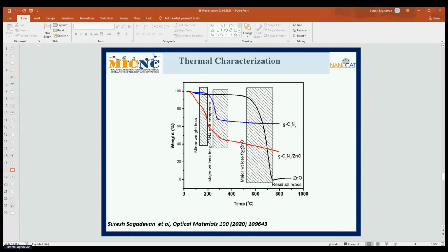Finally, in the case of graphitic carbon nitride and the composite, the significant weight loss is attained around the temperature of 450 degrees Celsius. You can see this clearly. You can see that the weight loss was attained around 450 degrees Celsius, which means the phase change of melamine into graphitic carbon nitride. So all the physical and chemical characterizations confirm the preparation of the samples and also the successful formation of this composite.